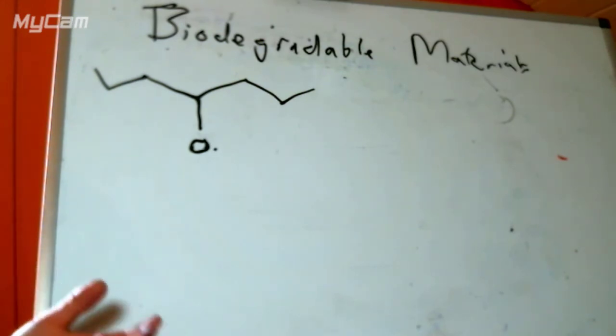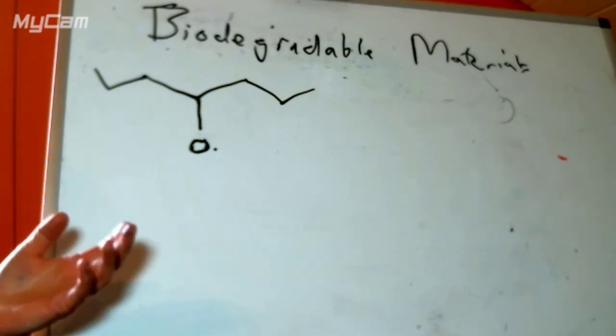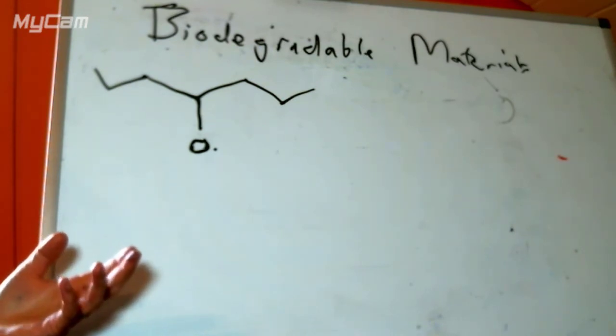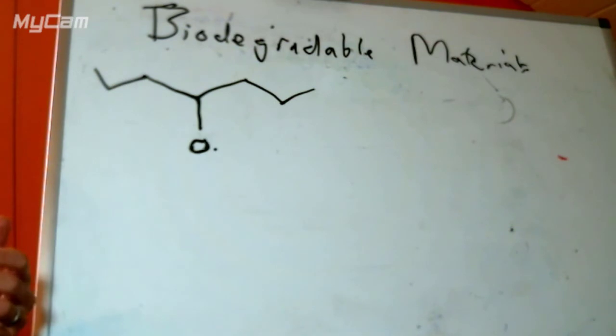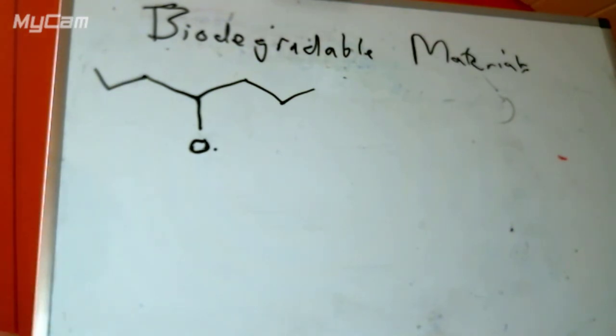So they would also have chains of non-polar material grafted onto them, so that they will be soluble in the polymer. They will be added relatively late, otherwise they're going to react with oxygen, and they will be mixed in with our polymer and effectively determine its lifetime.